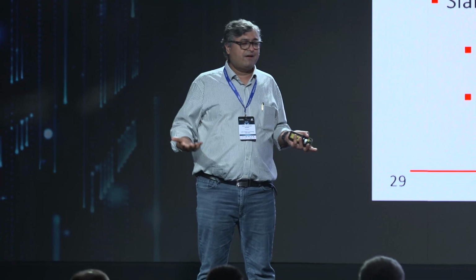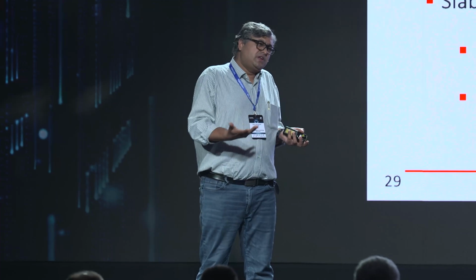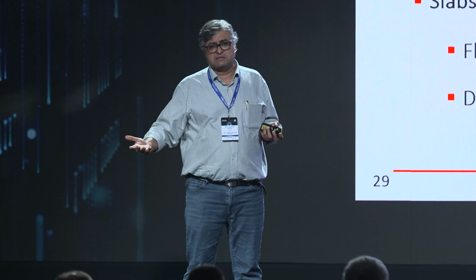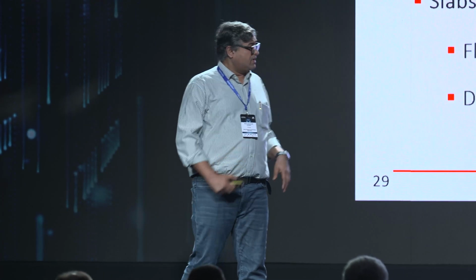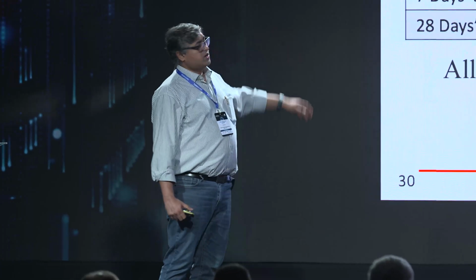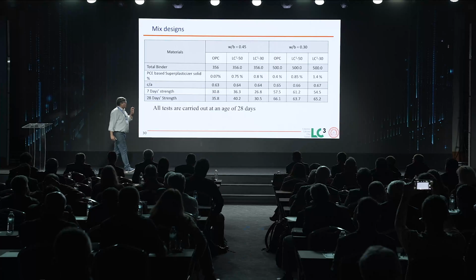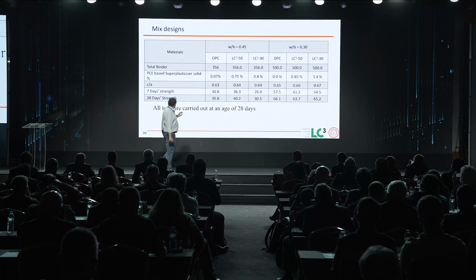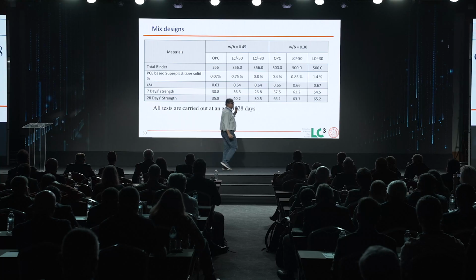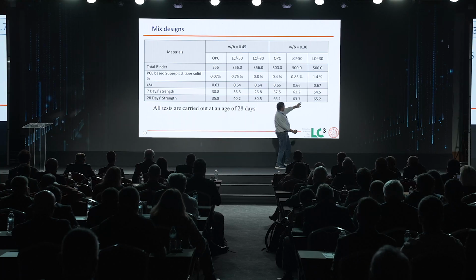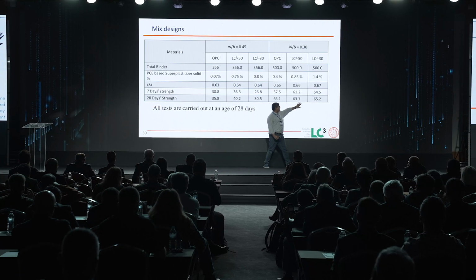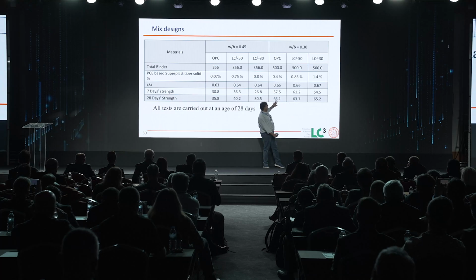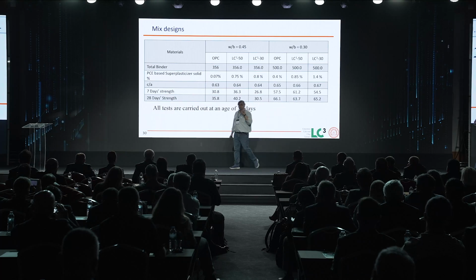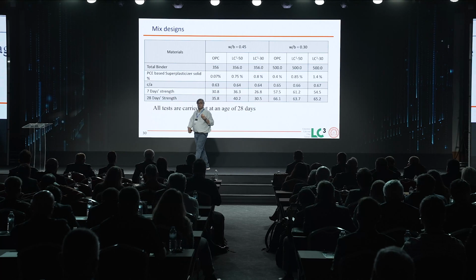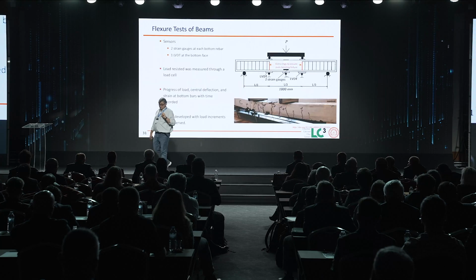We are essentially having the same loss of pre-stress because we realize it depends more on temperature than the cement type. But just to show you the results, we've been working on concretes even with 0.3 clinker content, and you can see even with 30% clinker content, you can design concretes to have a similar strength as 50% clinker and even as OPC. So with 30% clinker, you can still go to the similar kind of strength in the concrete.